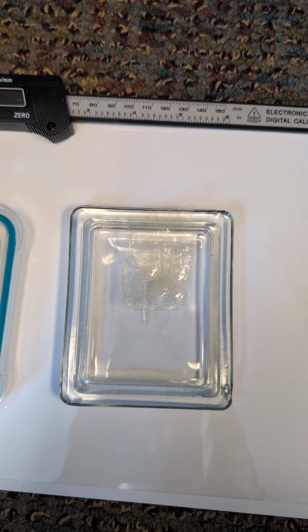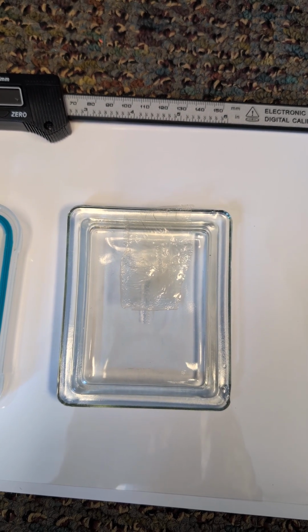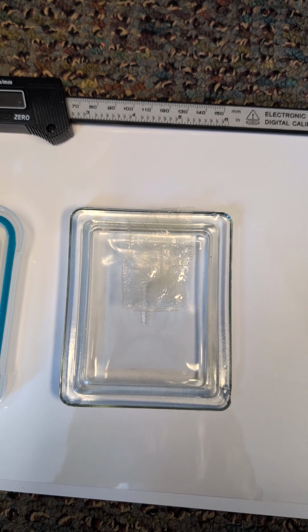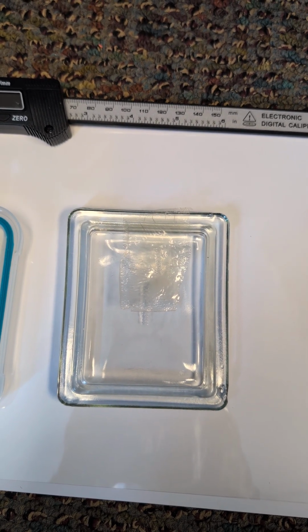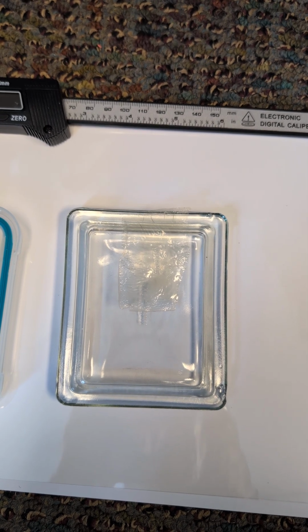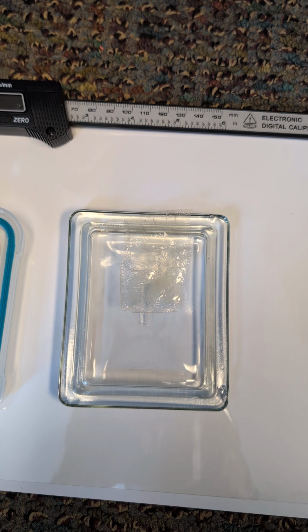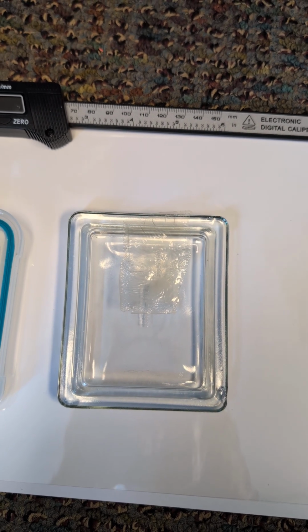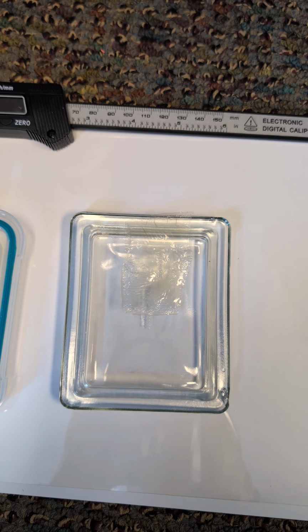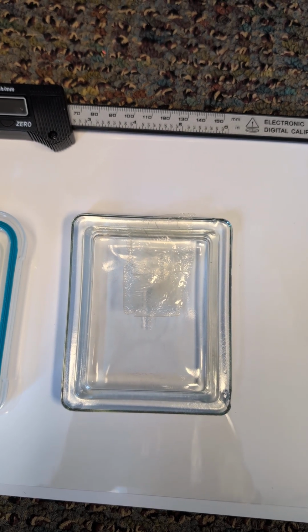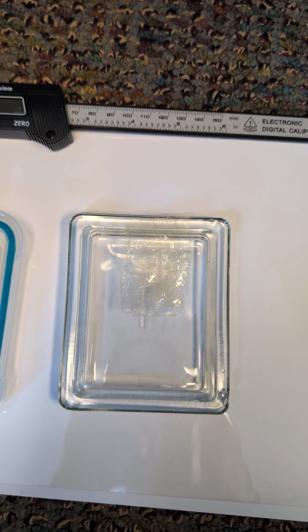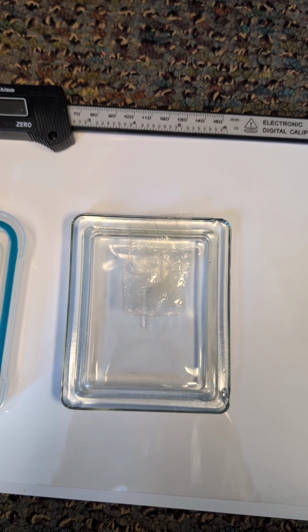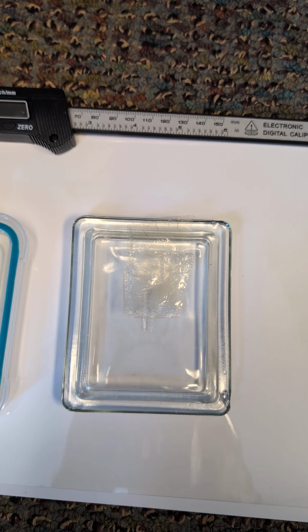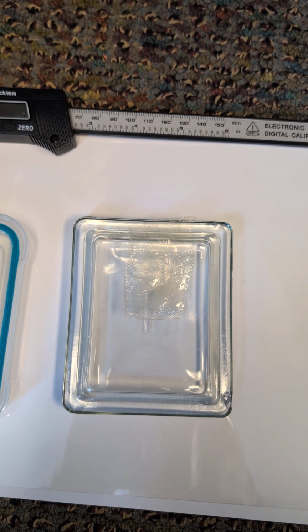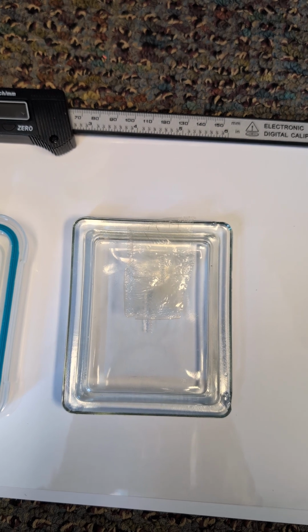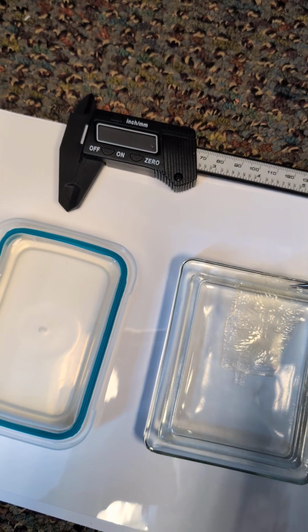Now, what you do at that point is up to you. Some will treat this film. If you don't do the sequence of events I mentioned, you will remove it after the thin film forms at the acetic acid point. If you don't heat it, it's going to form a jelly in water. The trick is the heating for that interval of time at that temperature, and then cool in place in the caustic bath. If you don't do that, it will become a jelly and you'll throw it away and that's the end of it. That's the trick.